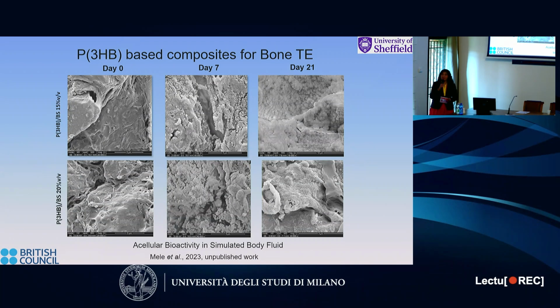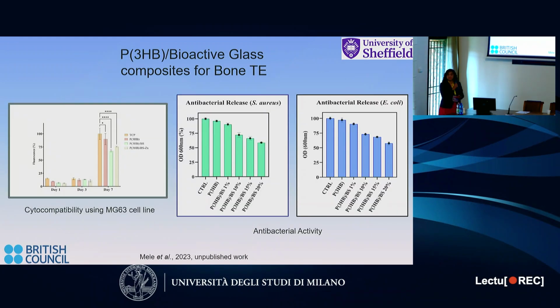We also wanted bioactivity. So this is simulated body fluid, just like the fluids in our body. We can simulate that fluid, soak your sample in it, and see where the hydroxyapatite forms, because bone is hydroxyapatite and collagen. And what we observed, all this irregular material that you see on the surface, is indeed calcium phosphate forming, and this told us again that this material is indeed promising.